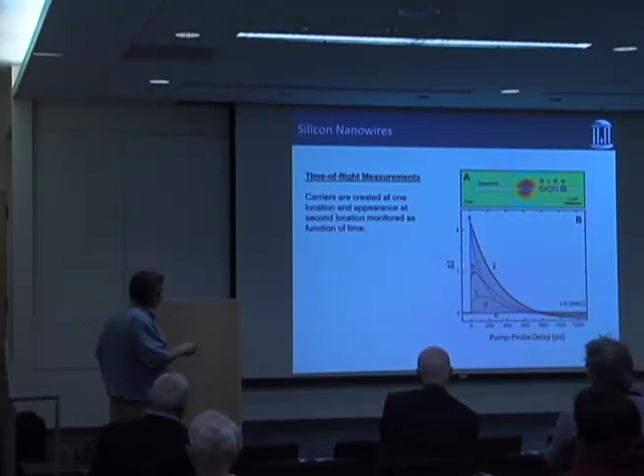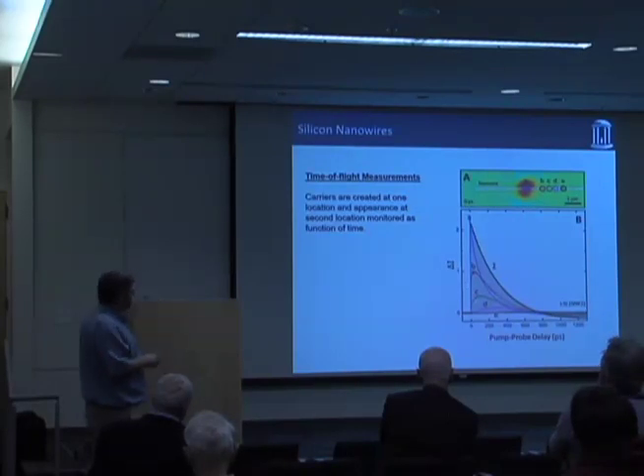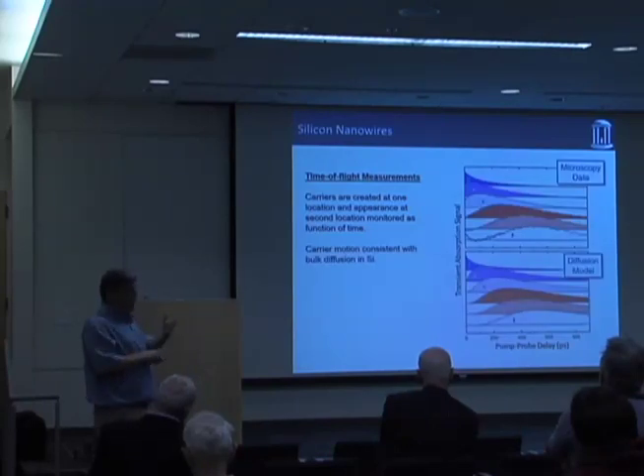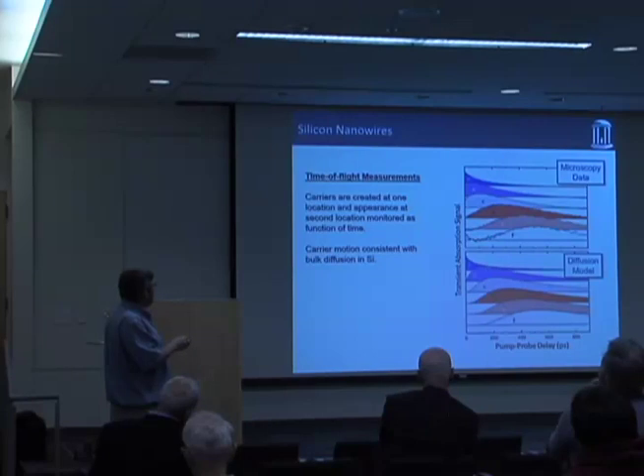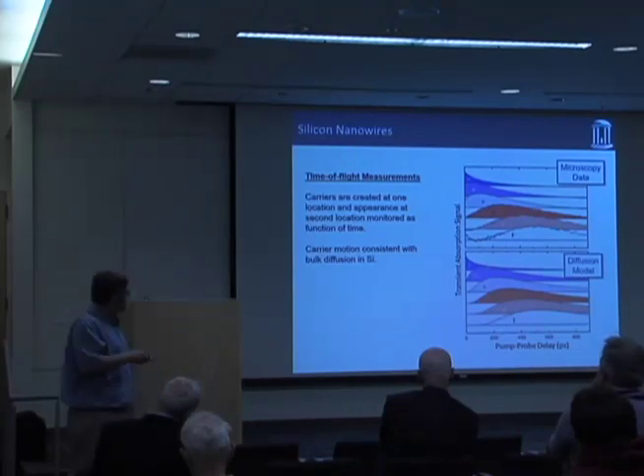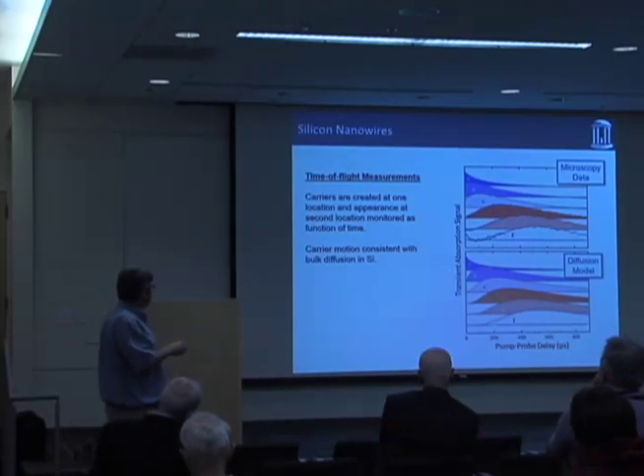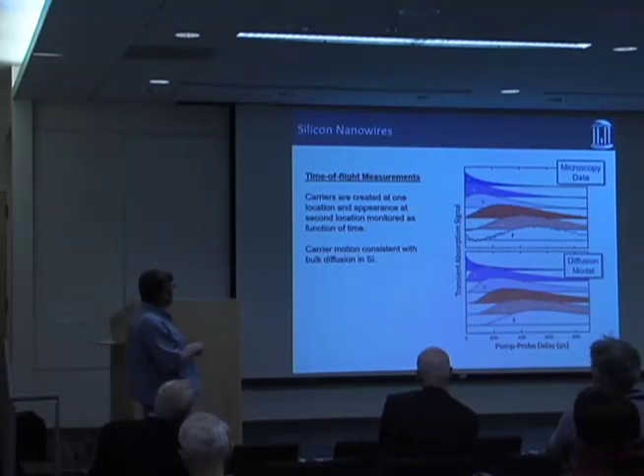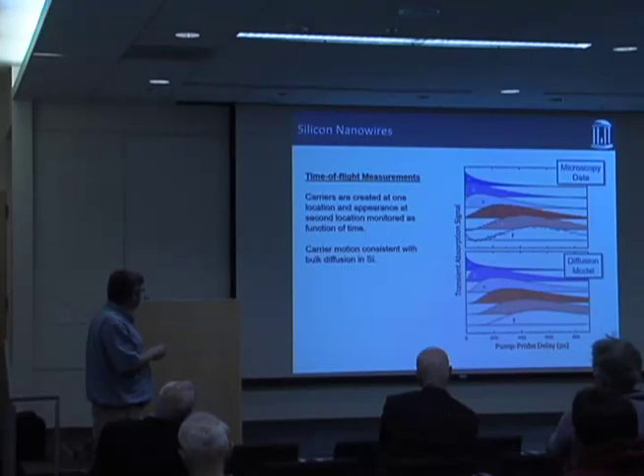And so when they're spatially overlapped, you see this really fast decay. It's essentially the same thing I showed you on the previous slide. But when the separation is larger, you see this delayed rise. So here, with B and C and D, we've got four traces here. There's E, you can barely see it. Turns out there's another one that's way down in the noise. So we're actually able to pull out, with pretty high signal to noise, the arrival of carriers at remote locations. And then you can ask, how does this compare with bulk silicon? So you do a simple diffusion model with bulk silicon parameters, and this is what you get. There are some small differences, but generally speaking, the carrier motion in these nanowires is more or less consistent with carrier diffusion in bulk silicon, which isn't all that surprising.